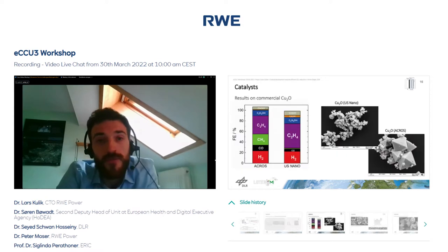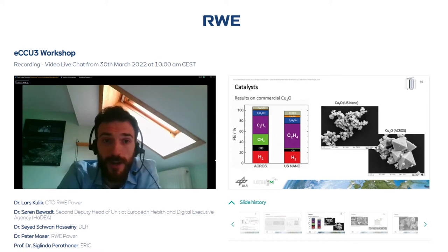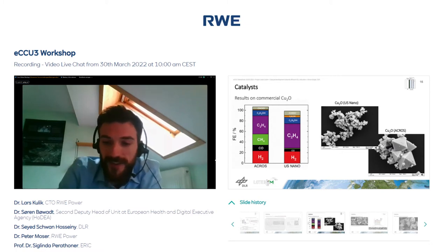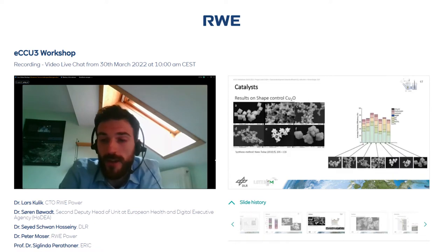On slide 16, you can see then the two main catalytic materials commercially available that we used, and compare these also with respect to the product distribution. And interestingly, we can see that this material ACROS that shows this octahedral species was producing more methane in comparison to the US nano material. And since we don't want to have so much methane, it's maybe more beneficial to have less diverse products, and then we chose now to use US nano as our catalyst.